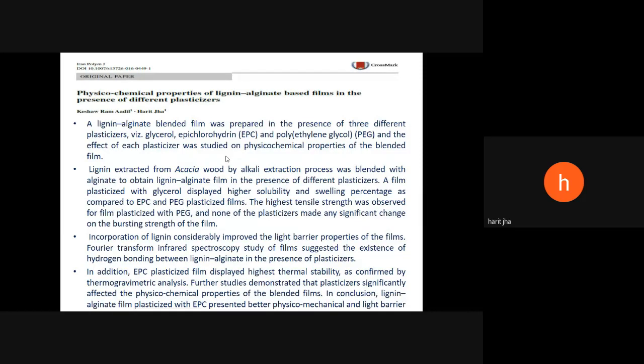So, alginate is a polymeric substance, a carbohydrate. Lignin is a polyphenol, and as lignin can easily form complex with carbohydrate in situ, we assume that when we use another carbohydrate and combine it with lignin, obviously a polymer will be formed. Alginate itself can also form a polymeric network, but when you add lignin and other plasticizers, it renders some improvement to the property of that particular polymeric film. And by rendering that improvement, like thermal stability and also the light barrier property, this biodegradable polymer's quality and strength can be improved.